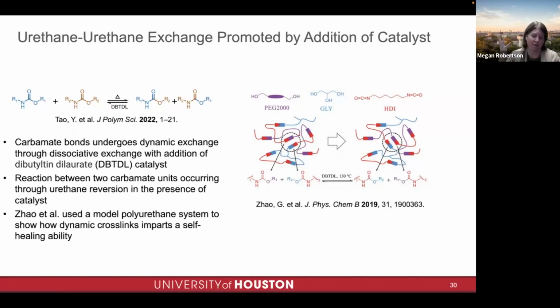And this polymer, if we heat it up in the presence of this catalyst, we can process it at high temperatures, just like a plastic. So even though it's a thermoset, which traditionally you cannot heat up and remold and process, if you have this exchange catalyst, you can actually do all of that. You can use melt extruders. You can process it any way you would normally process a plastic. And so that's what we did.